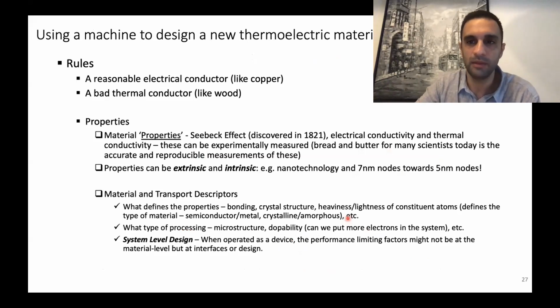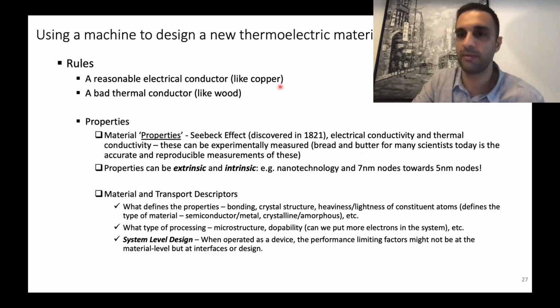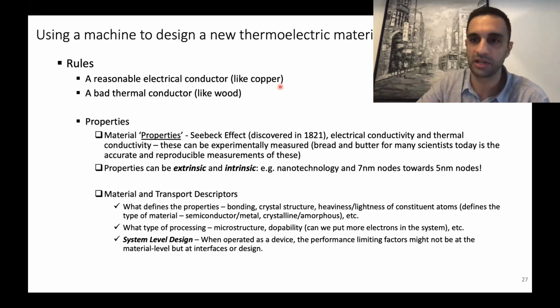competitive value. So if you were to actually task a machine to design a new thermoelectric material, what would you do, right? How would you actually give it the task? What you would tell it is, well, the rules are that it has to be a reasonable electrical conductor. It has to be a semiconductor, highly doped. But at the same time, it has to be a bad thermal conductor, like wood. So that's an ideal phonon glass electron crystal material that we are all trying to discover.